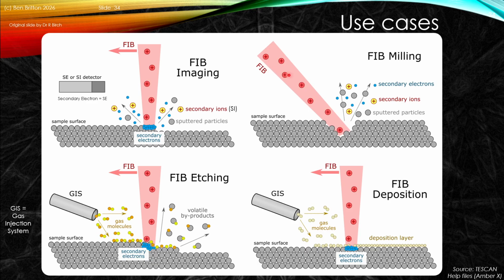If we introduce the FIB into our sample, we can sputter the material away, and so we can mill. To help us, we'll often put the sample at an angle to the beam, not always, but that's just what this cartoon is showing. We might also use the gas injection system, the GIS, and we might introduce a gas molecule that effectively enables us to avoid the sputtered particles from sticking back to the surface.